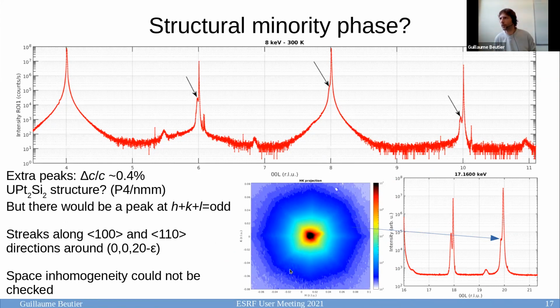What is also interesting is that if you look at a local HK map around one of these peaks, you can see these streaks here that go towards the HK direction, but also the HH directions. So these are attributed maybe to domain boundaries of this phase. Unfortunately, we could not check the spatial homogeneity of this phase on the samples because we did not have time to do that.